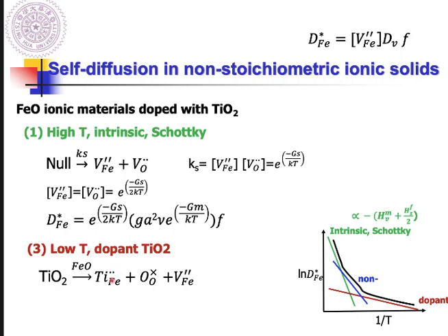This is a two positive charge, right? For sure, there's a negative charge here to reach neutrality, so you will get the vacancy at the iron site. Based on this, and also based on the previous derivation, you know that in the dopant dominant region, the vacancy fraction at the iron site will be equal to the fraction of dopant.